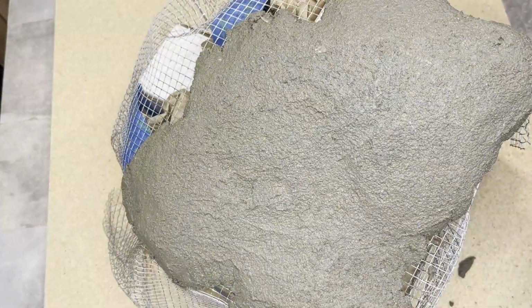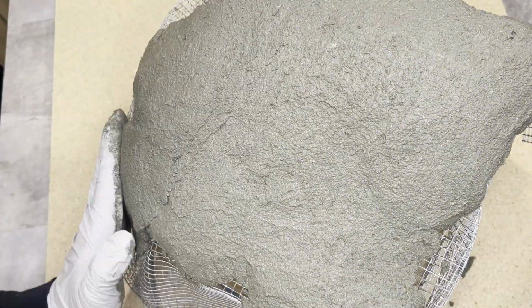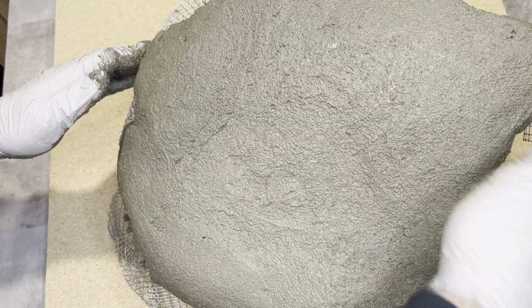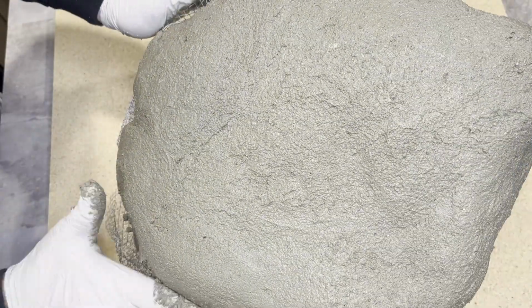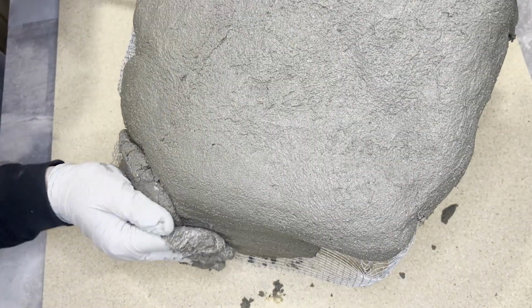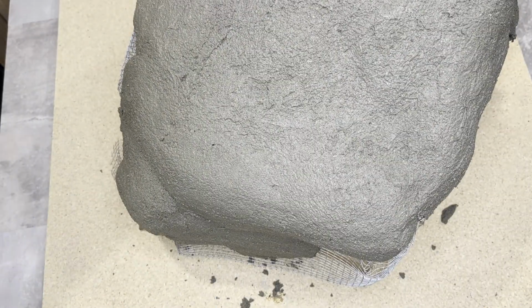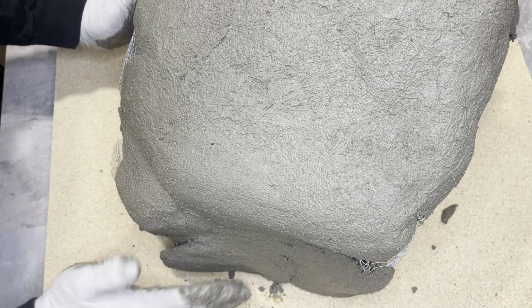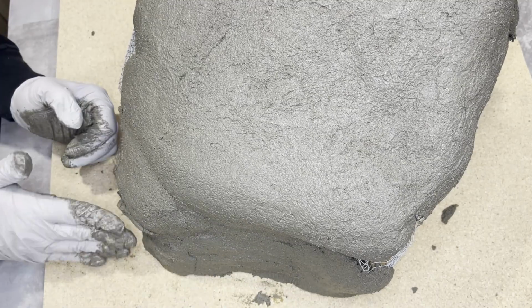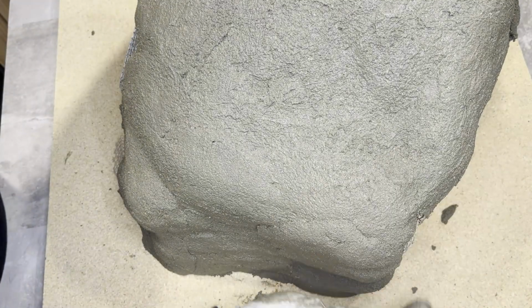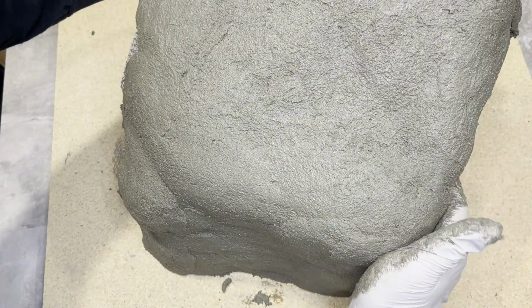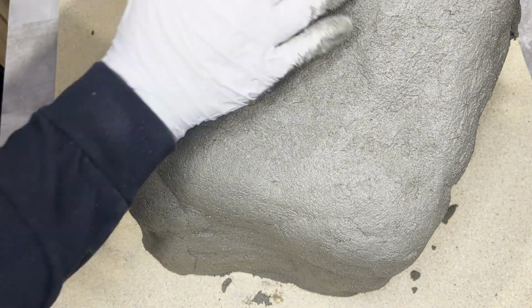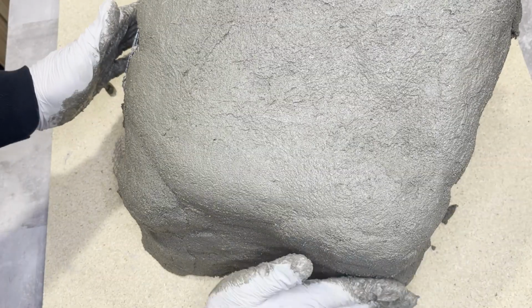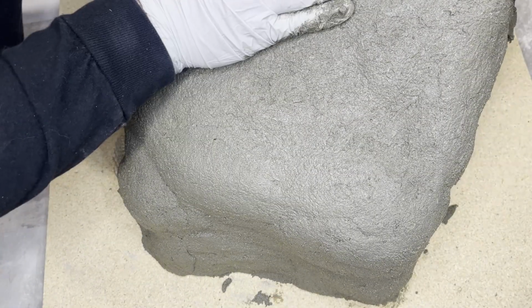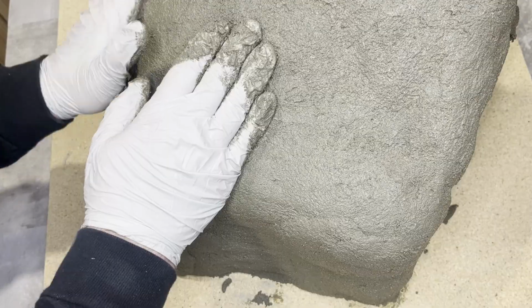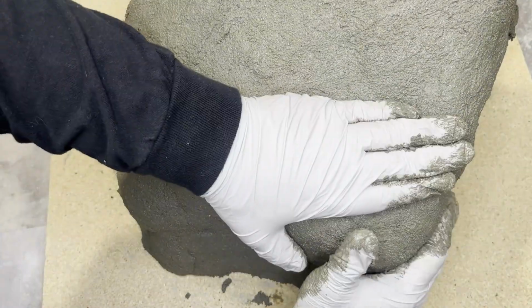As with all cement-based products, the material should be allowed to cure for a minimum of 28 days prior to submerging in water. The toxicity of Portland cement to fish, when added to water, is attributed primarily to the high or alkaline pH produced upon hydrolysis. Allowing the product to fully cure for 28 days greatly reduces the risk of changes to pH and allows the product to become non-toxic to aquatic organisms. A few full water change cycles are still recommended once the concrete is added. Always check the pH prior to adding live animals.